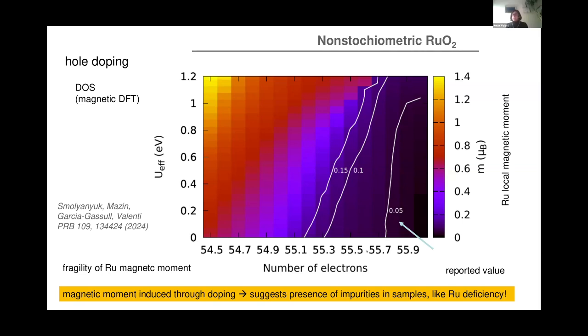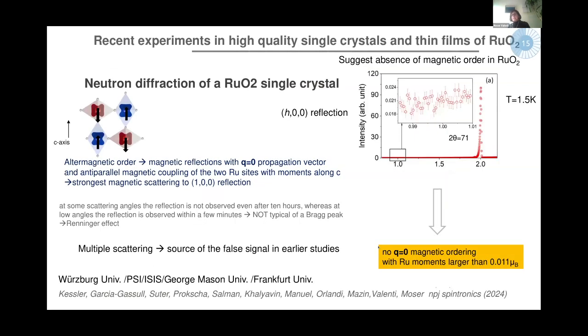So this is what this calculation suggested, that we may be having an issue with the samples. And we know, in fact, I didn't put the references here now, there are some references that indeed indicate that there are some ruthenium vacancies in the samples. So what we next did is then, together with our collaborators in the big facilities where they do neutron scattering experiments at PSI, as well as muSR experiments at ISIS. So basically, they had high quality, both single crystals and thin films. And basically, they did a very careful analysis of what neutron diffraction gives for these crystals.